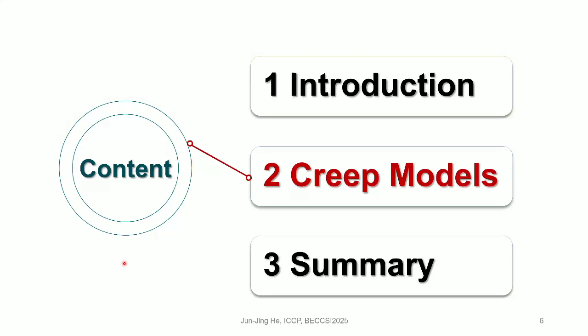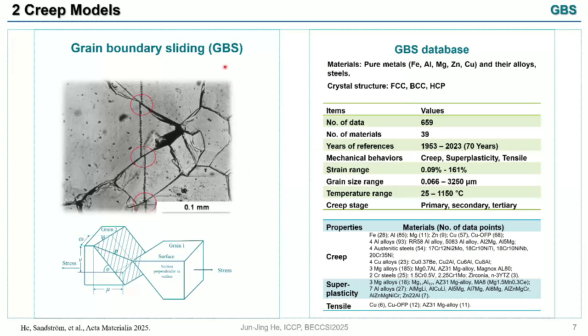And then we go to the creep models. Grain boundary sliding is the basis for both the creep cavitation and the brittle creep rupture. In our recent work, we have established a systematic grain boundary sliding database, and it covers a very wide range of materials and conditions, including the pure metals and their alloys and steels. This database covers 70 years of references and also a very wide strain range, grain size and temperature range.